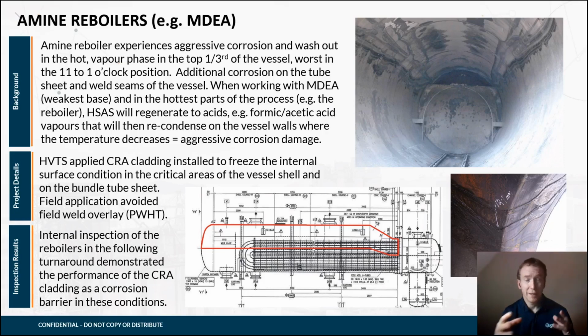As well as the amine columns, the strippers, the absorbers, the regenerators, we also have the amine reboilers. So these are locations where we have high temperatures, we get potential breakout of these bad actors causing very aggressive localized corrosion and often erosion corrosion because of the turbulence and the fluid motion inside the vessel. So this is a typical example where you get a washout of the top of the column from your sort of 12 o'clock position outwards to 11 and 1 o'clock, and that's where you're losing significant metal.